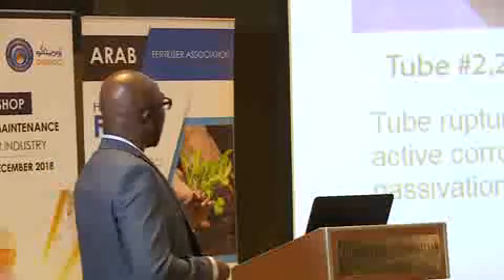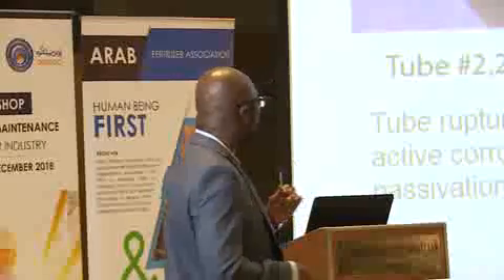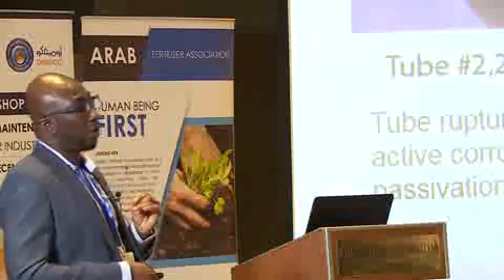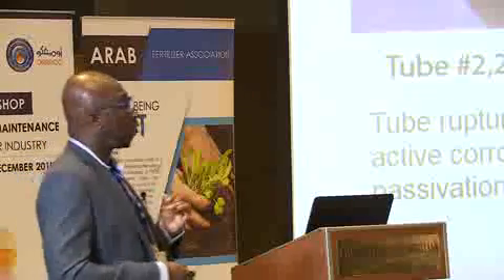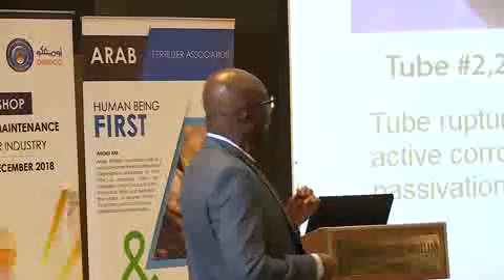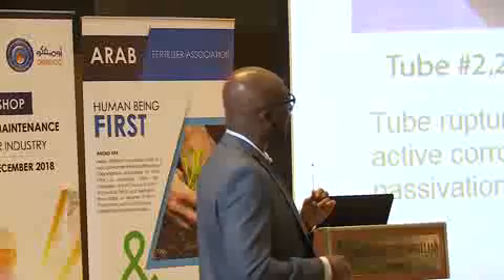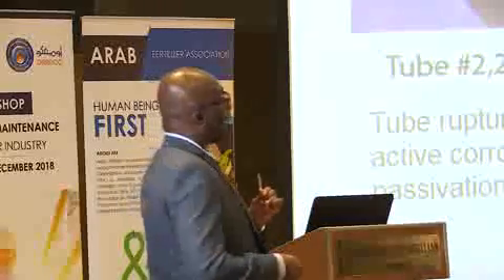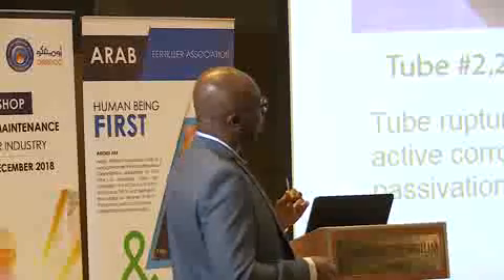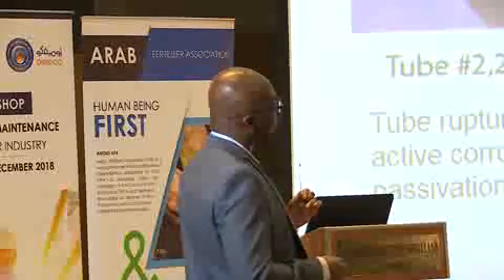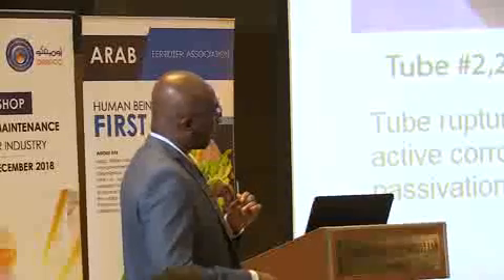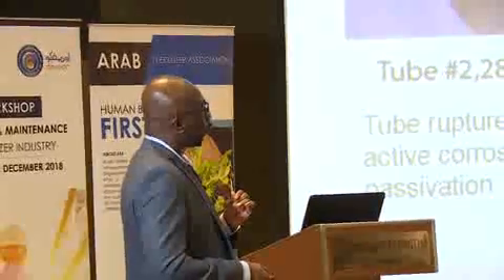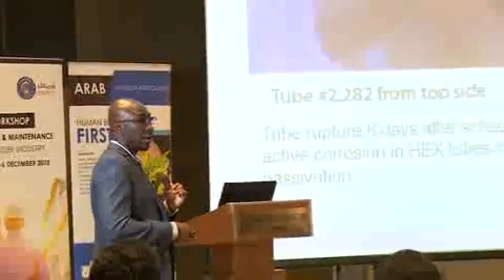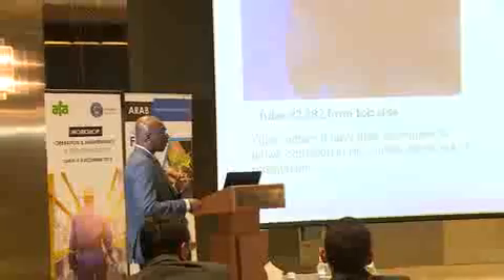This picture is an unfortunate event that happened for a client. Eight days after a turnaround, they had to shut down the plant because they had a tube rupture. And what happened? I think during the turnaround, something was left in the stripper tube. And when operation started, this created a block. So you created stagnant conditions, high temperature. The oxygen and CO2 that are supposed to come from the bottom of the tube could not reach this area. So, of course, after just eight days, the tube ruptured, and then the plant had to be shut down. And this is a tube that is made from an austenitic stainless steel material.